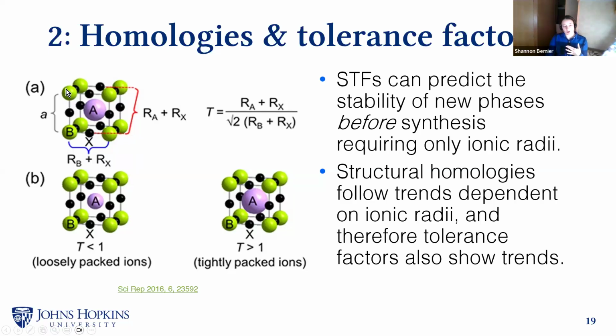It was specifically for use with perovskites, which always have the same bonding arrangement like this. And it's basically a measure of thinking about how spheres of a fixed radius can pack into the unit cell and minimize the amount of empty space. So you're trying to figure out what the ideal value of this metric is in order to create a perovskite. This has been used extensively in the literature for perovskites, and it does a reasonably good job at predicting whether a combination of atoms will be a perovskite. And it's also been tweaked a little bit to make it more effective and applied in other situations for other kinds of bonding environments. In other words, for other structures besides what's called a perovskite.